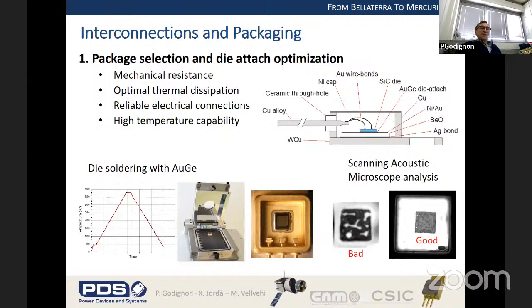So this is a wrong result, and the good result is the right one, where you see that the voids between the die and the package are very few. We have only two small white dots. So in this case, the device can be considered as okay.